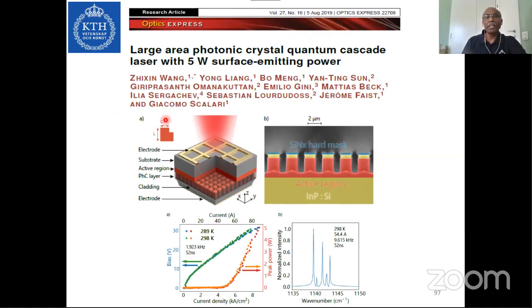Of course, we collaborated with the group of Professor Jerome Faist, one of the inventors of QCL, now at ETH. They invented it while he was in the labs. This is the cartoon, and here is the cross section of the photonic crystal structure. Here is the active layer, and here is the regrown iron doped indium phosphide. These are all very, very small structures. We can grow on very big structures, but also on very small structures. And we could obtain 5-watt surface emitting power. It is room temperature, but not continuous wave operation. You can see here it goes up to 5 watts.